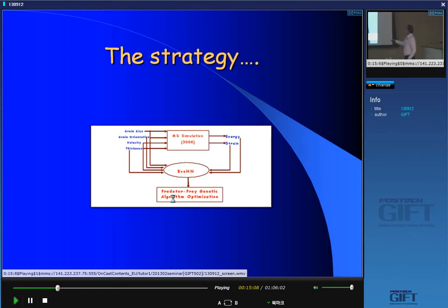But anyway, we have these variations, and through MD simulation of the assemblies that I have talked about, I can shear it. I can follow its energy absorption till it fails, and when it fails, I can measure how much it has deformed. That is the measurement of the strain. And these are the parameters that I want, because I want this energy to be as large as possible, and I want this strain to be as low as possible.